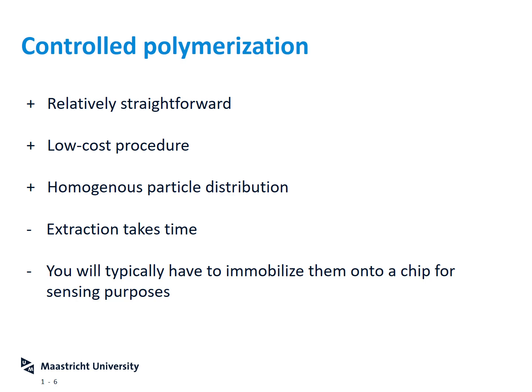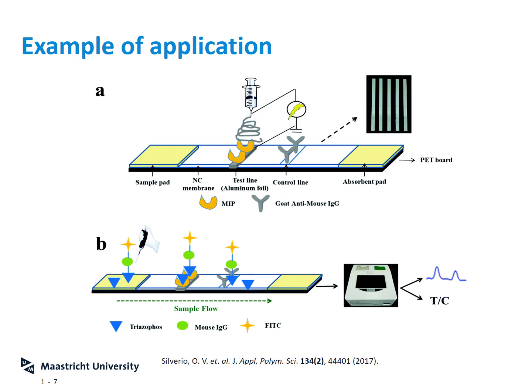to detect your target. To give you a relatively recent example, by Silverio and co-workers from 2017: before we talked about the pregnancy test, well, they made a similar lateral flow assay where they changed the test line, where you usually use antibodies towards your target, and you use MIPs instead. So what they then do is take a sample that contains the target, which is a pesticide, Triazophos, and to that sample they add the target coupled to an antibody and a fluorescent molecule.